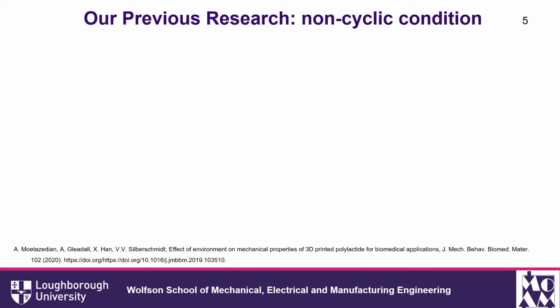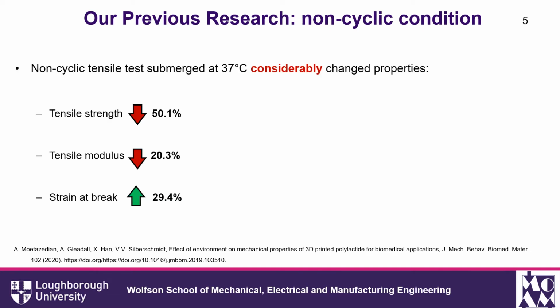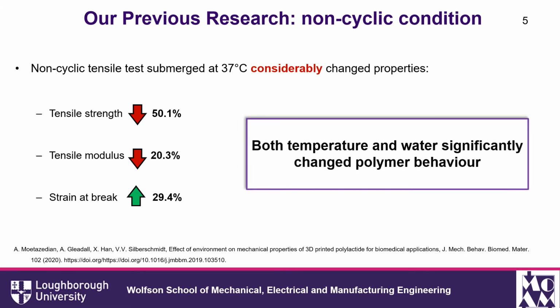One of the motivations for us to do this experiment was based on our results in the previous studies. So for non-cyclic tensile testing submerged at 37 degrees, we found a considerable reduction and changes in the properties. For instance, we identified that tensile strength and tensile modulus were reduced by 50 and 20% respectively. Meanwhile, the strain at break was increased by approximately 30%. And we identified that the synergistic effect of water and temperature was responsible for the change in the behavior of the polymer.